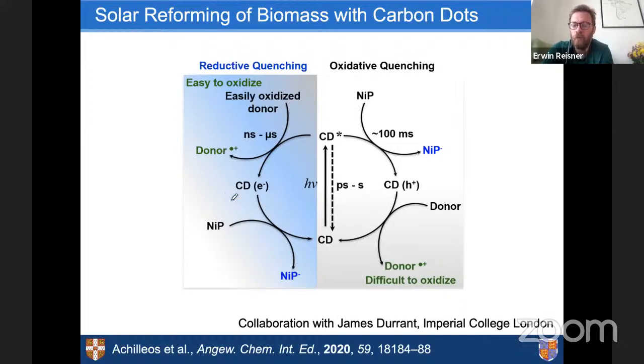We end up with a reduced carbon dot that can then reduce the nickel catalyst, and upon two reductions, we can form the hydrogen. If we don't have a suitable or highly reactive electron donor, and we would consider this, for example, for the cellulose, especially when it's still insoluble, then we form this fairly long-lived photoexcited state that's still long-lived enough to oxidatively quench with the nickel catalyst, forming the reduced state, which can then make the hydrogen. And then you accumulate these oxidized carbon dots, which effectively in the dark can start reacting with the donor.